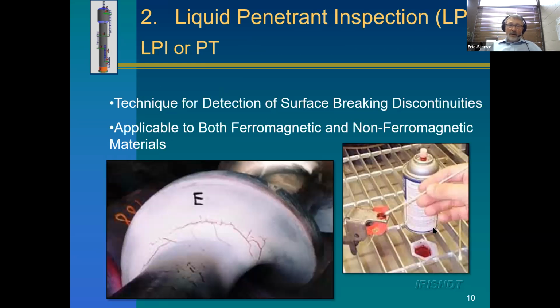So the second technique we're going to talk about is liquid penetrant inspection, which is LPI in Canada or penetrant testing, PT in the US. And with those ASME codes, it's all PT. And this is the same kind of deal as magnetic particle inspection. It only finds surface breaking defects, and usually it's used on non-ferrous materials because you can't do MPI on that. You can use it on both ferromagnetic and non-ferromagnetic materials, but it's more expensive than MPI, so we typically only see it on non-ferromagnetic materials.